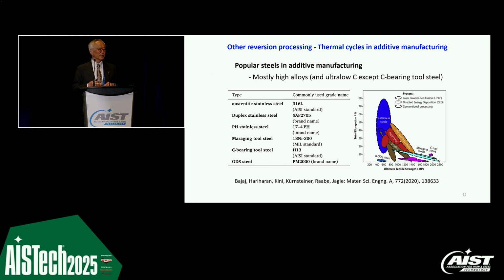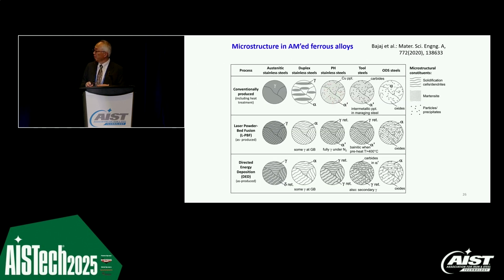Now, of course, all over the world additive manufacturing is popular, and for steels, relatively high alloy or high carbon steels, a lot of work has been done applying such thermal cycles in additive manufacturing. Perhaps for the high carbon steel, we can have phase transformation take place. So during the thermal cycle in additive manufacturing, we may get actual grain refinement by controlling the reversion treatment.